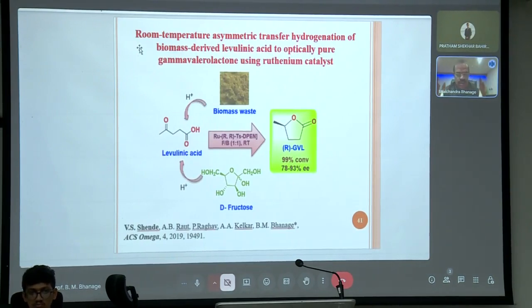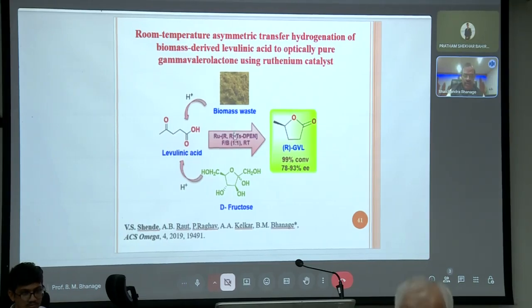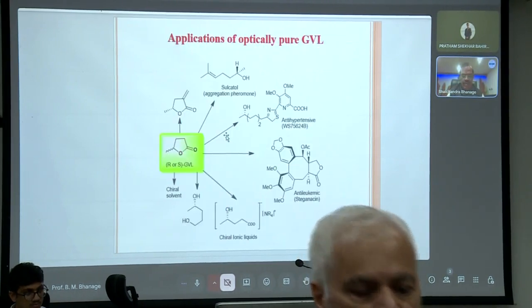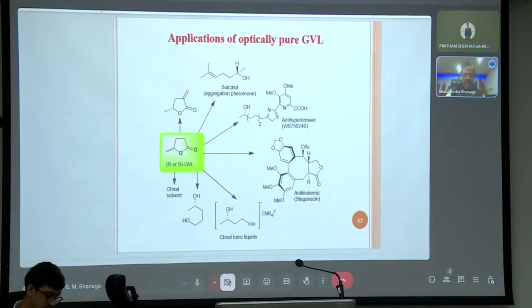Then levulinic acid we have converted to GVL, that is gamma valerolactone, and here for the first time we have attempted to prepare chiral GVL, and there was no report of chiral GVL from levulinic acid. So we have taken biomass waste or fructose, converted that into levulinic acid, and we have developed here a homogeneous form of catalyst using transfer hydrogenation reaction with ruthenium based catalyst. This is the catalyst, and sorry, this is the gamma valerolactone.